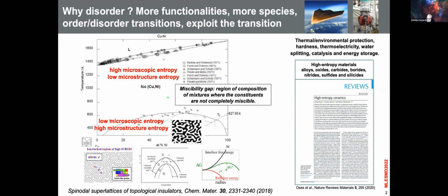Note that when we as physicists discuss order and disorder, we really believe that order is really, really order and disorder is really disorder. In reality, there are a lot of things in between. In disorder, you can have high macroscopic entropy, meaning that if you mix the red atoms with the blue atoms, you have some color in between and no microstructures. And when you have order, you might have an ordered set of microstructures, but inside you might have a disordered population. So the way to have order-disorder is not really like what we do with the Ising model, where you go from completely order to complete disorder. And therefore, it's much more complicated and we need to address it.